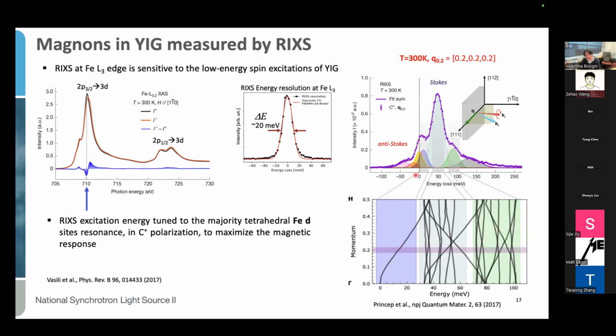Starting at 0 energy, we have our elastic peak, and then around 10 meV, we can find another peak that corresponds to the acoustic ferromagnon mode. And here, I'm selecting the Q that we use for our measurements. Around 50 meV, we have a strong peak that is likely the collection of all these optical branches here. And at higher energy, we have another peak that corresponds to the higher energy optical magnons, while we still have spectral weight above 100 meV, where no single magnons should be present, but it is very common in RIXS to find peaks associated to multi-magnon processes. And because we are measuring at room temperature, you may notice the presence of finite spectral weight in the negative energy loss region, which is due to the presence of anti-Stokes modes.